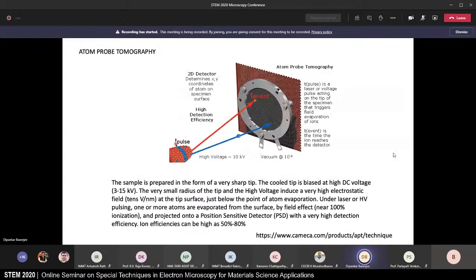I now want to conclude, and these are my last few slides, on another technique which complements transmission electron microscopy. And this is atom probe tomography. And the idea is that you can emit atoms from a very sharp tip through the application of a field or laser pulsing. You can analyze the time of flight of those atoms, and you can relate the composition of those atoms to the position in this sharp tip. And therefore, you have the potential of looking at the three-dimensional structure with chemistry information.